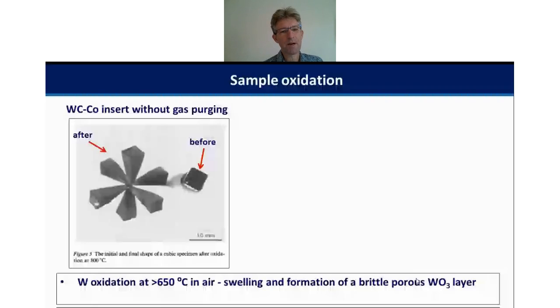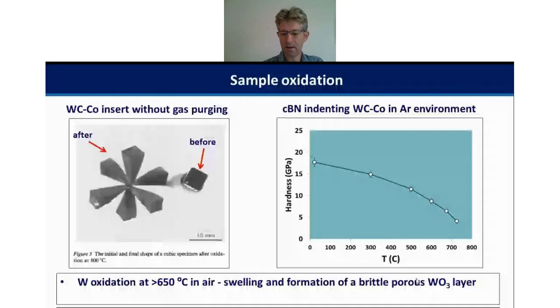So we also need to worry about not just the indenter but also the sample. I particularly like this picture. This is from Frank Lofi, and in this case it's a cemented carbide insert that has just been exposed to an 800 degrees air environment, or possibly a pure oxygen environment. You can see the little cutting tool insert, the square insert with the rounded corners, before testing, and the rather dramatic shape change that occurs due to this swelling and formation of tungsten trioxide. Even though such extreme things don't necessarily happen in nanomechanical testing, it is still something you need to worry about, and it's not really possible to test once you get oxidation, because essentially then you're testing the oxide properties and not the properties of what is underneath.